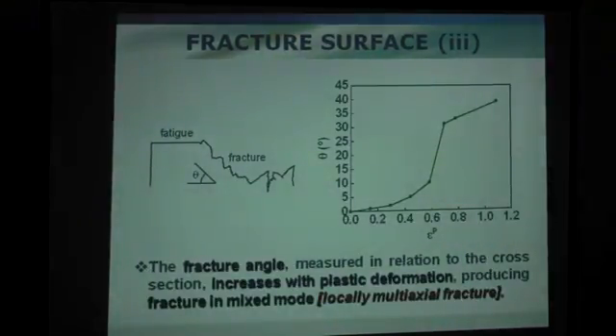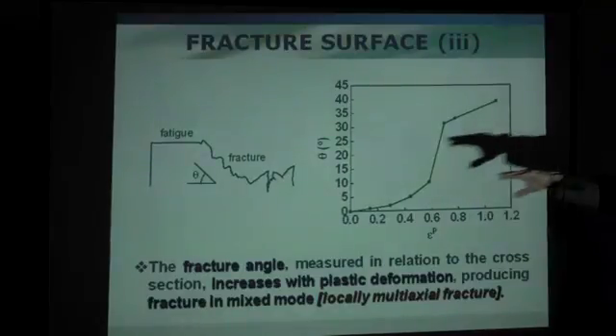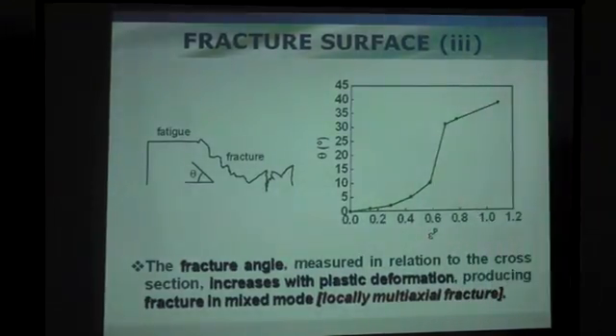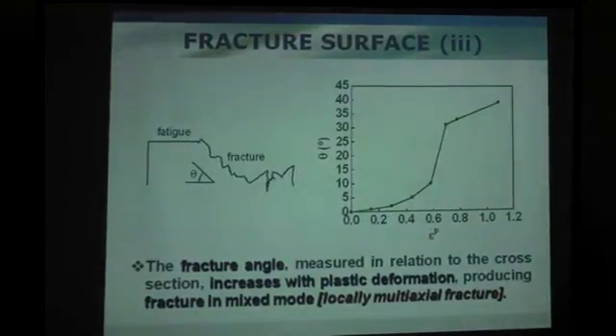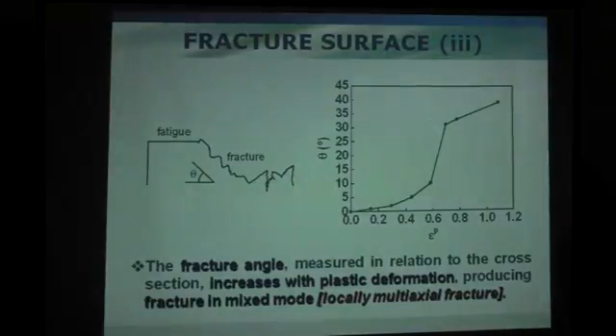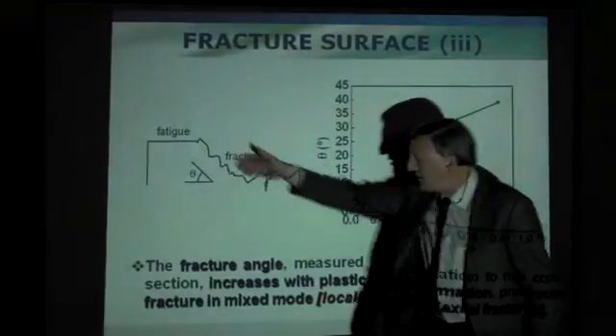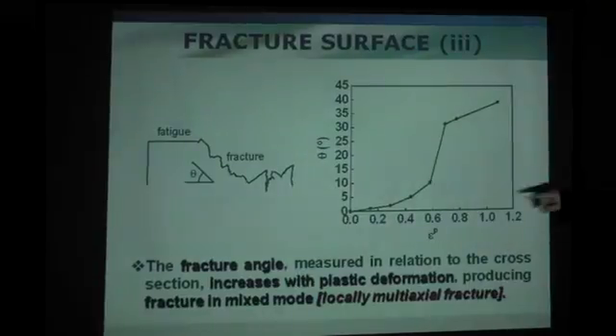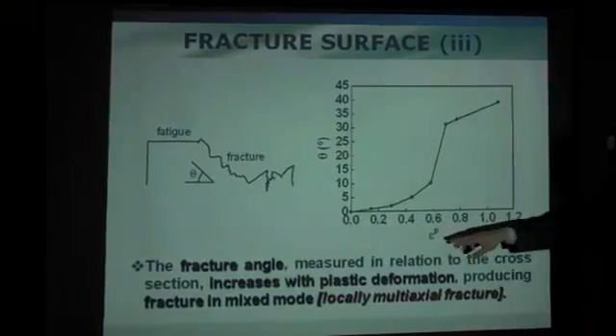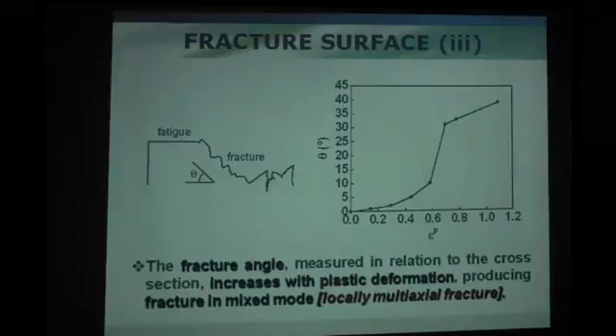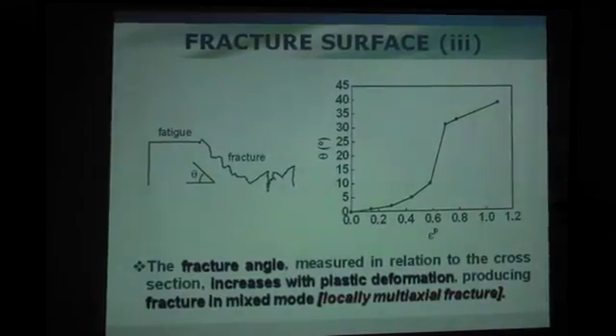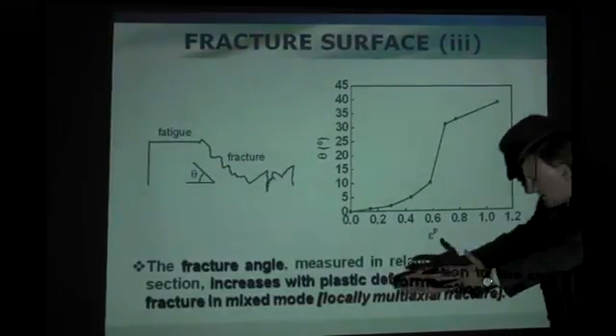Here we have the profile in schematics, the fatigue. An interesting question is, why does fatigue propagate in mode 1? With local mixed modes, with local deflections, but in global mode 1, fracture takes place in mixed mode propagation. The fracture angle theta, the macro angle, measured in relation to the cross section, also increases with plastic deformation from the drawing manufacturing process, producing fracture in a mode we could define as locally multi-axial fracture.